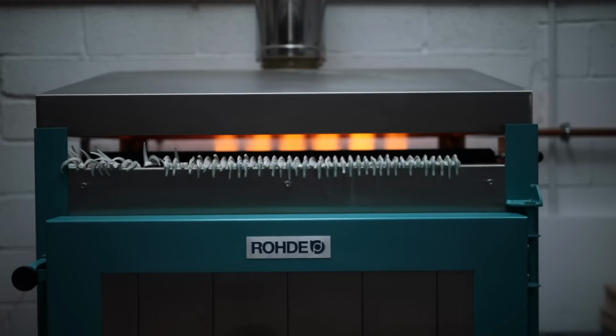If I fired them in a fully oxidized atmosphere, like what's found in my electric kiln, these same glazes would fire to rather mottled yellows and browns, which aren't nearly so nice. As the temperature approaches 1290 degrees Celsius, I periodically tap the dampers open just a fraction so the temperature keeps rising, and then, once all 3 cones are bent over, the kiln can be switched off.